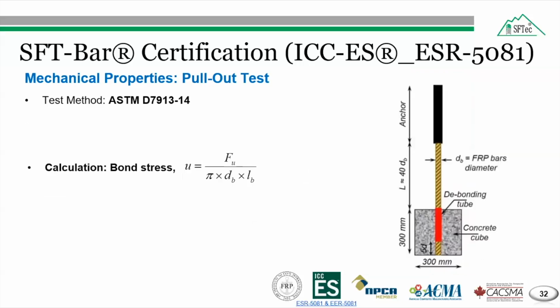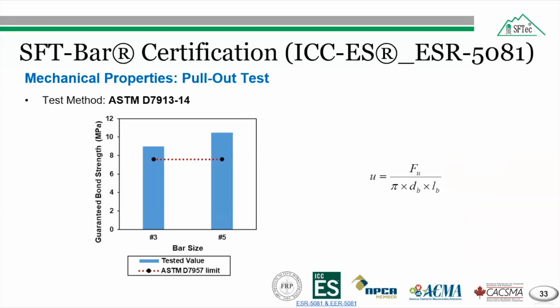So the bond stress at the peak load was calculated assuming a uniform bond stress distribution along the embedded length of the GFRP bar in concrete, and that is along the length equal to 5 times the nominal diameter of the GFRP bar. And for the SFTech bar, the average bond strength was above the requirement. The requirement is around 7.6 megapascal as per ASTM D7957, and both number 3 and number 5 exceeded this requirement.